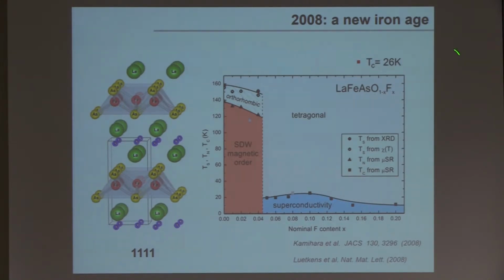I would like to talk about iron-based superconductors that show a very similar phase diagram to the high TC cuprates. So basically, these materials are layered materials also, but instead of copper and oxygen playing the important role in the systems, it's iron and arsenic or selenium, so pnictide or the chalcogen atoms. And these systems are, in fact, metallic, but most of them show long-range magnetic orders, so spin density wave-like.